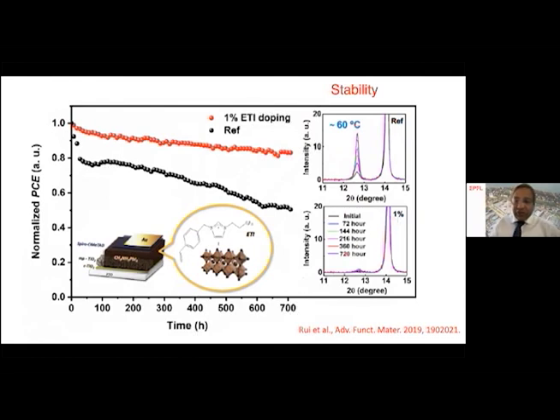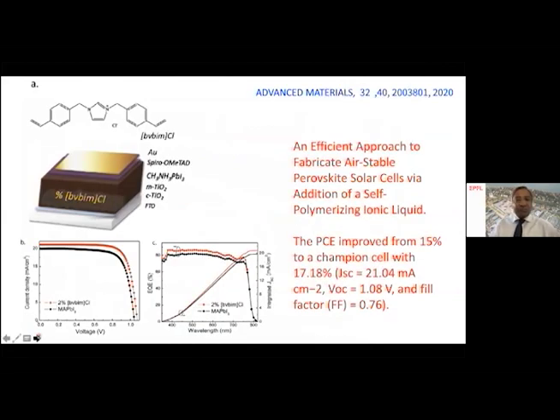And with the 1% ionic liquid, even when we subject it to 720 hours of stability testing, the data shows absence of formation of lead iodide. So this is the beauty of this material. Let me take one more example. This is another ionic liquid. This work is published in Advanced Materials.